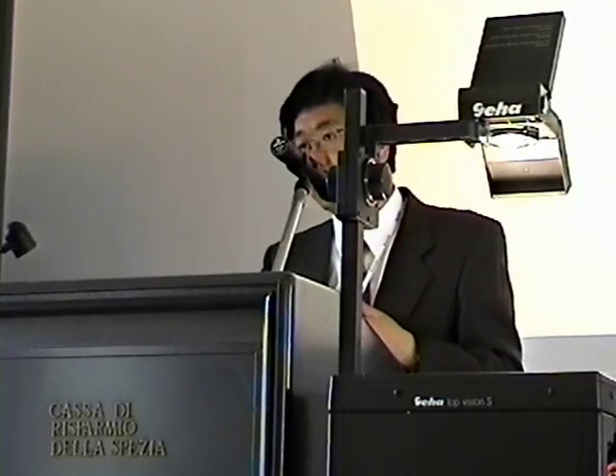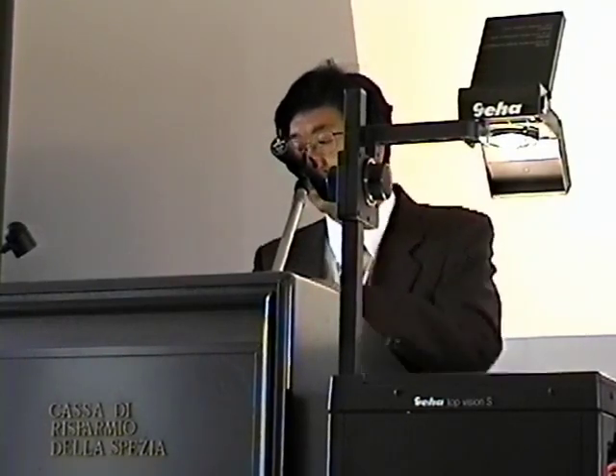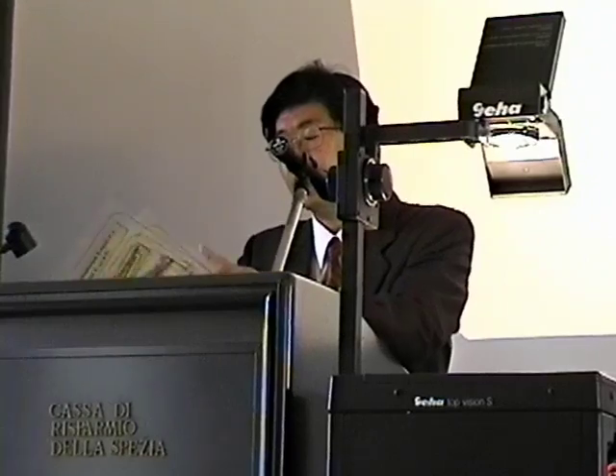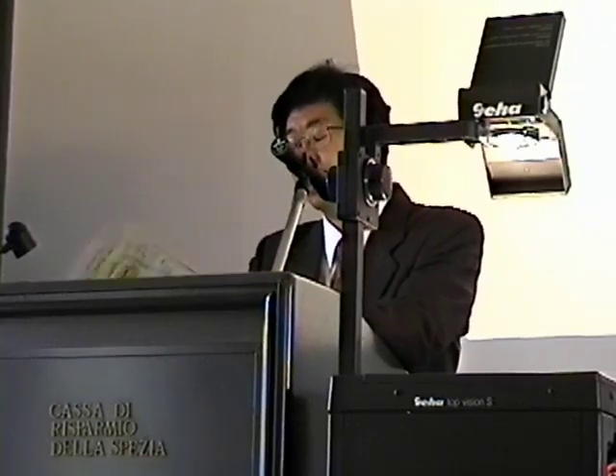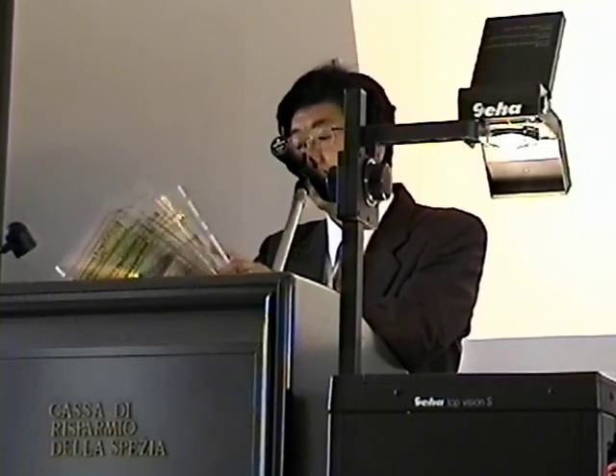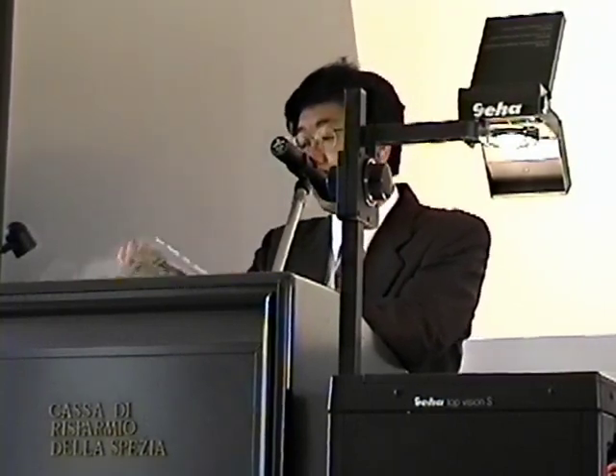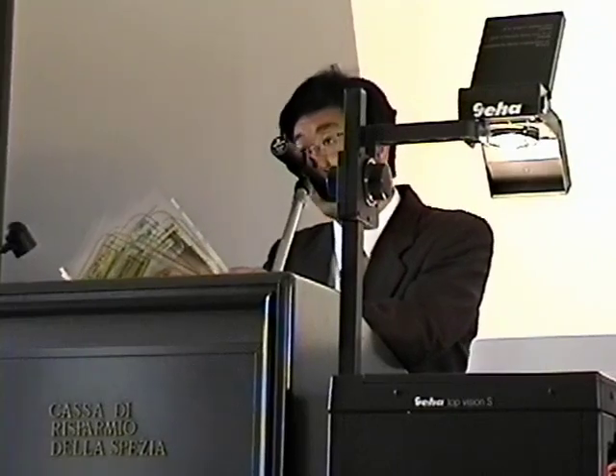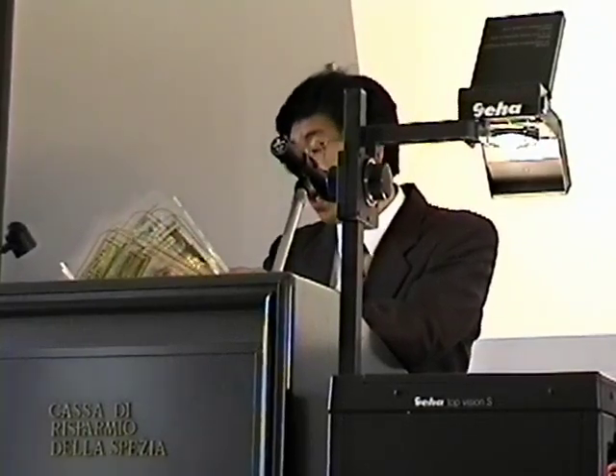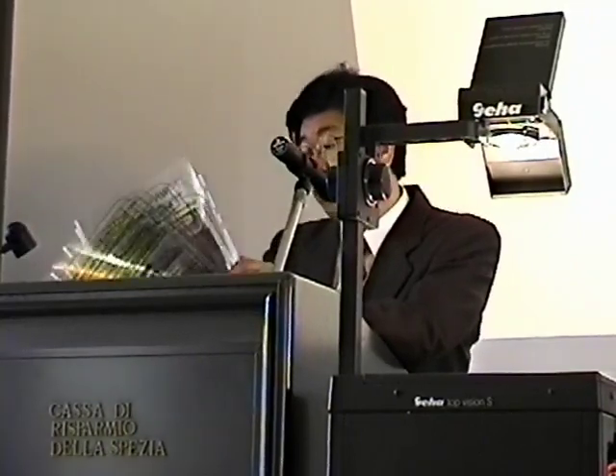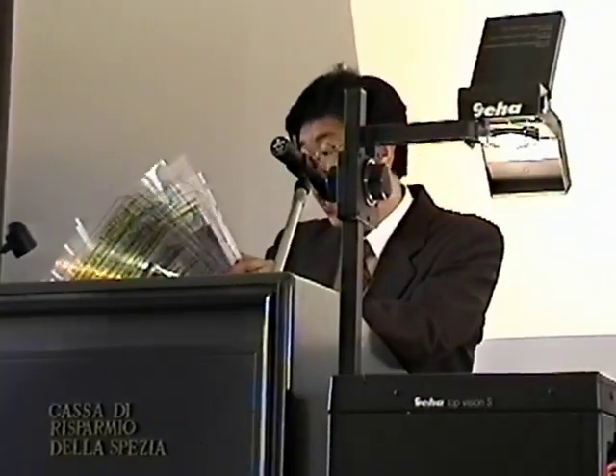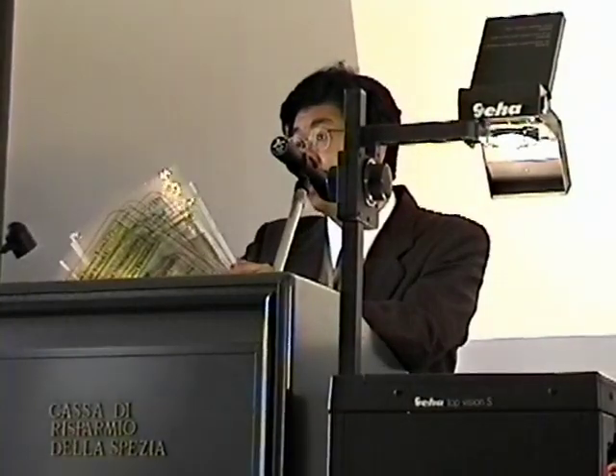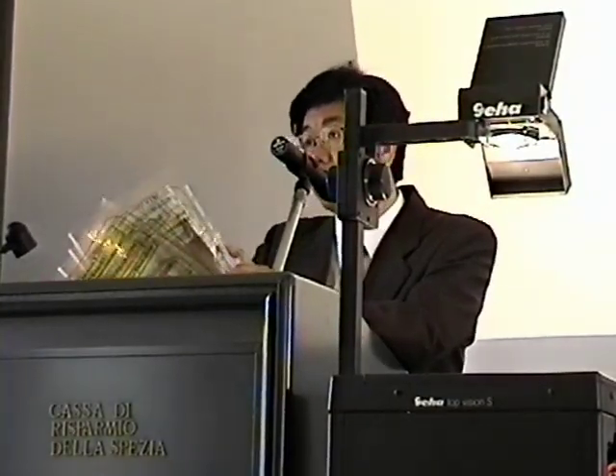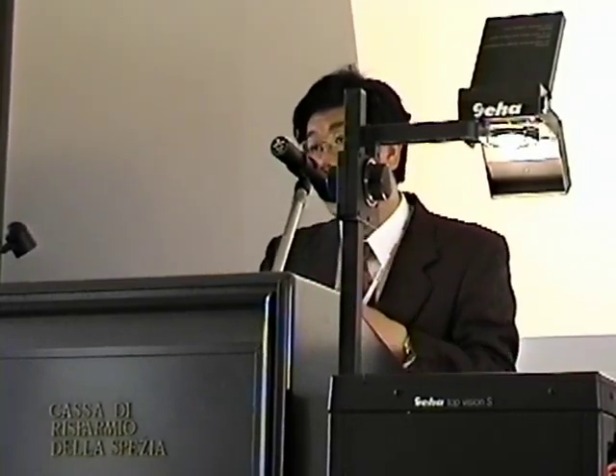Okay, and another question please. The accuracy of XPS is quite bad for light elements like carbon. You haven't plotted the error bars on those plots. Is the variation of the concentration considerably larger than the error bars for those data points? It is difficult to detect carbon by XPS, you say? I think so. We specified it by the other method, so we think it is attributable to carbon.